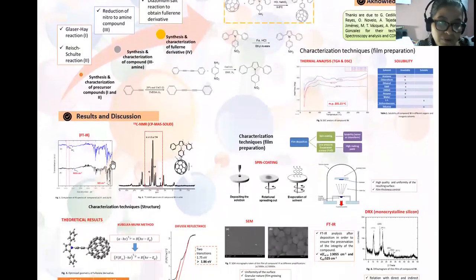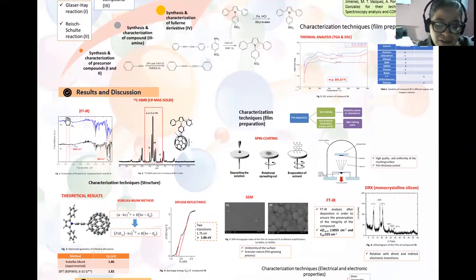Subsequently, the product obtained was characterized by infrared and nuclear magnetic resonance to obtain information on its structure. In the infrared spectra, the absorption bands corresponding to the amino group at 3413 and 3331 inverse centimeters disappear. And the pyrrole characteristic band is visible, as well as those at 1427 and 524 inverse centimeters, which are attributed to the C-C and C=C bonds on fullerene.